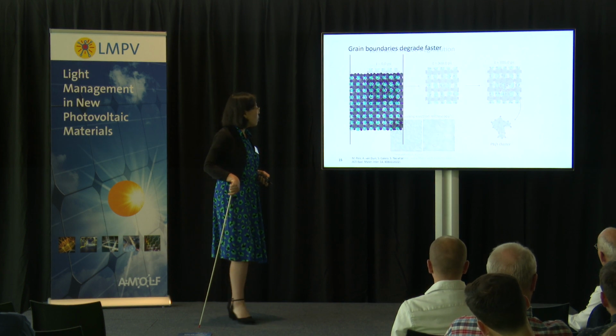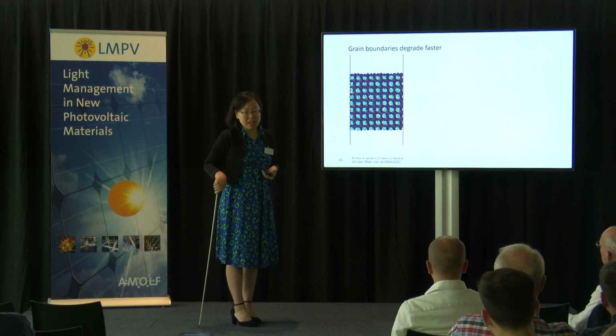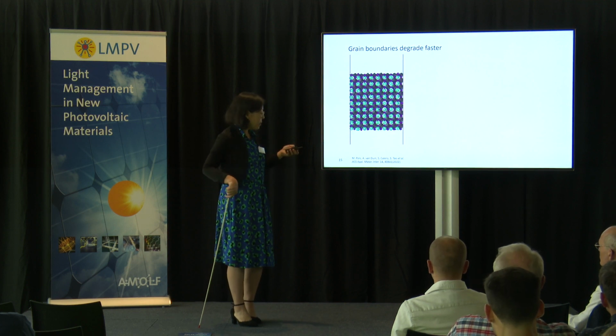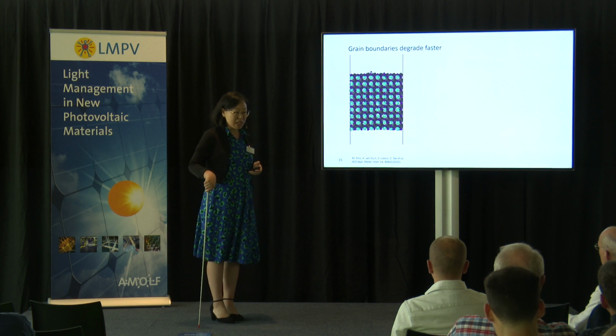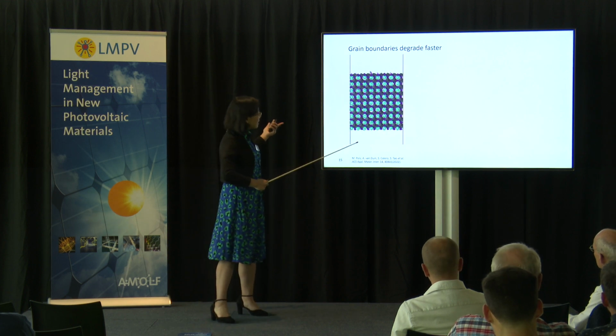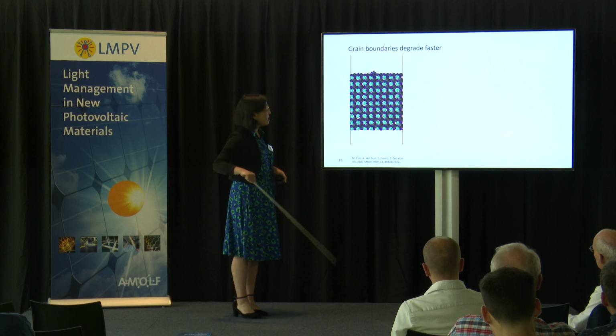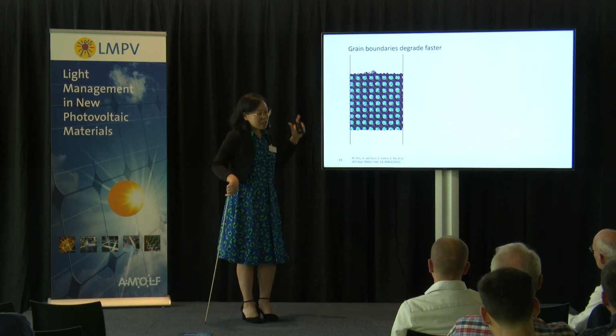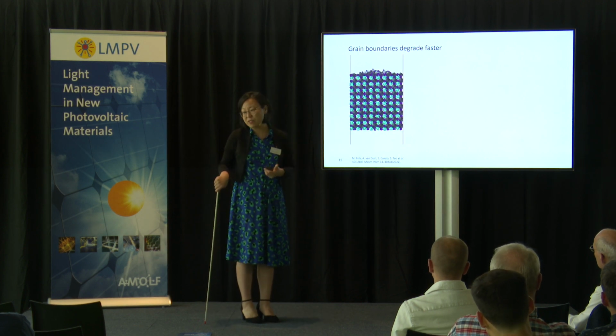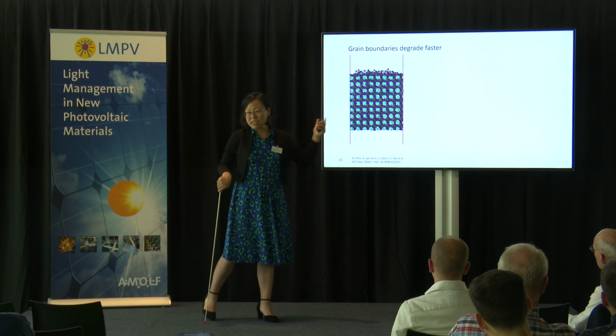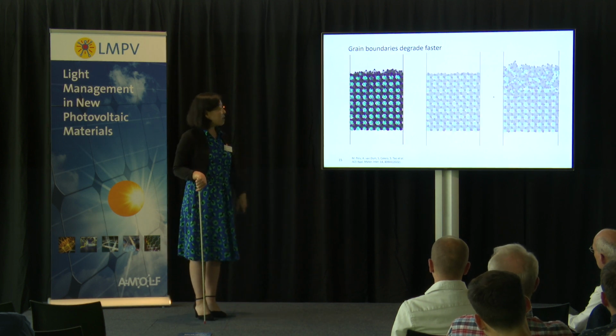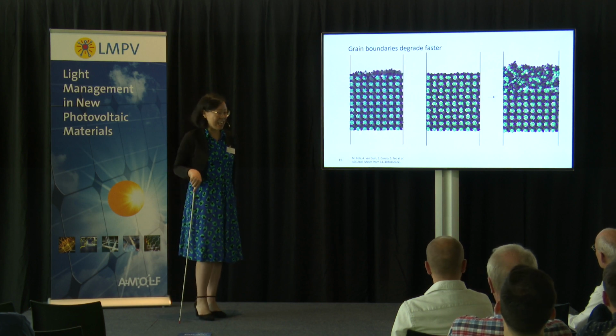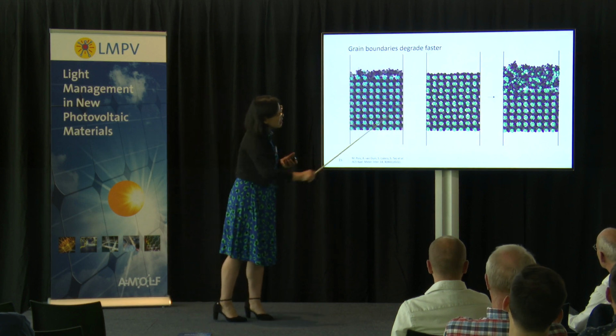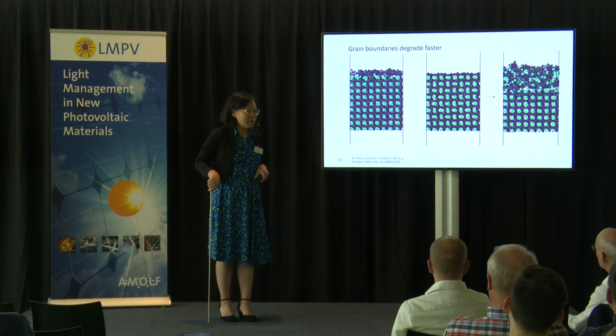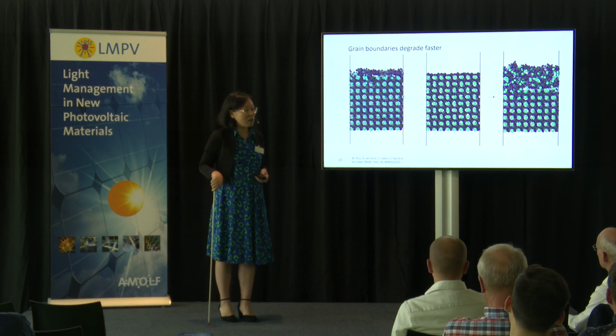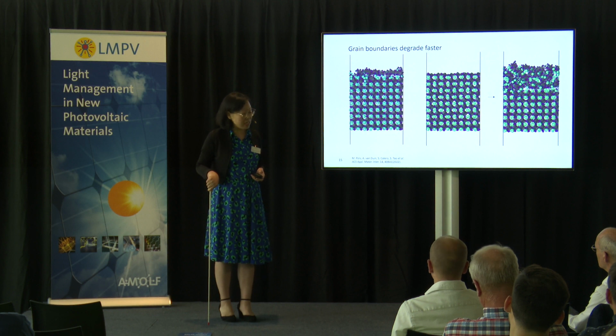What about more extreme defects like surface, grain boundary? We did the same simulation on the slab. This is a cesium lead iodide with 2 totally different terminations. If you look carefully, the top surface behaves totally different than the bottom surface. I will give you the result already while you look at the atoms. The top surface totally becomes an atom soup, and the bottom surface is wholly stable and remains intact.